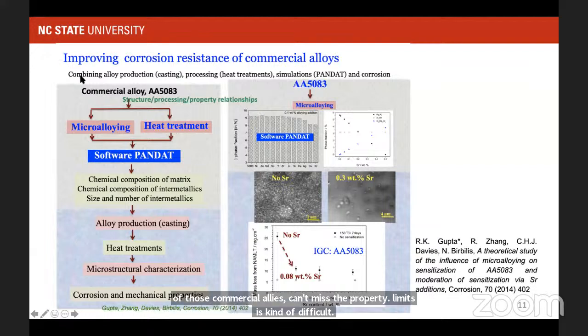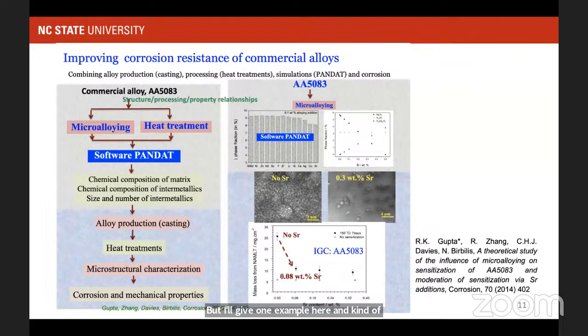But I'll give one example here that shows how we can work on the commercial alloys and solve those very specific problems. So here is one example for 5083 aluminum alloys. This is an aluminum magnesium alloy, used quite a lot in making ship hulls and things like that, right? And this particular alloy has 4.5% magnesium and a little bit of manganese. And the problem with the alloy is, it's highly corrosion resistant, but once we put it in service and the temperature exceeds, say, 50 degrees centigrade, the supersaturated solid solution of aluminum magnesium decomposes, and an anodic phase we call Mg2Al3 precipitates at the grain boundaries, and then the grain boundaries corrode, and you have huge intergranular corrosion issues, right?